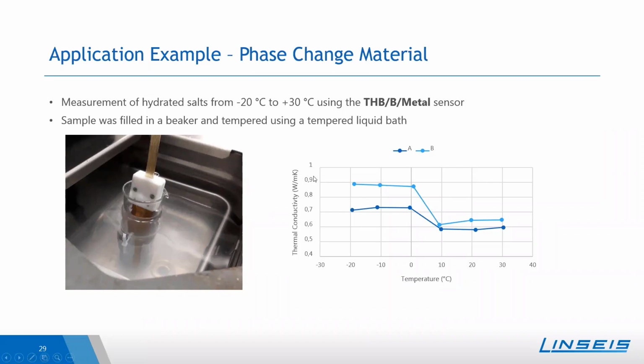Within the results of the thermal conductivity in dependence on the temperature, one can see that the different phases of these phase change materials can be directly seen also in the thermal conductivity results. At room temperature, going down to 10 degrees Celsius, the material was more or less liquid, and shortly below 0, it started to be solid. And this can be clearly seen here in the thermal conductivity results.